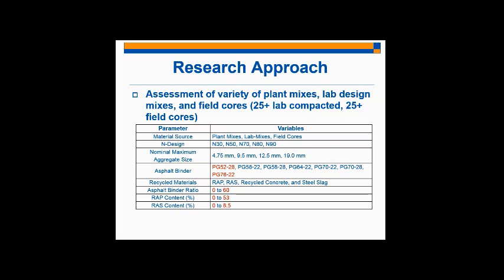We have RAP, RAS, recycled concrete, and steel slag. And we have asphalt binder replacement percentages of 0 to 60%, so we get pretty high up there. RAP content ranges from 0 to 53%, and our RAS content ranges from 0 to 8.5%. So we've really pushed the envelope with how different we can make our mixtures, to make sure that whatever criteria we develop is robust enough to analyze all kinds of different mixtures.